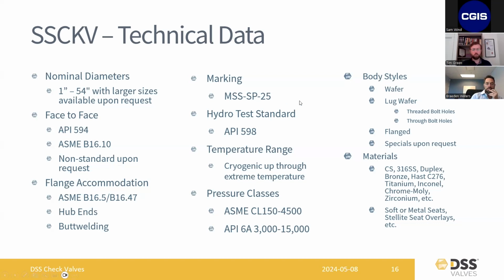Each valve's marked per standard MSS requirements. They're all hydrostatic tested. So every valve gets a hydrostatic test before it leaves the factory. But also because of the temperature range, like I mentioned, we can do cryogenic testing all the way up through any kind of high temperature testing that's required as well. We do ASME class 150 up through class 4500. And then also we can get into the API 6A pressure classes all the way up to 15,000.